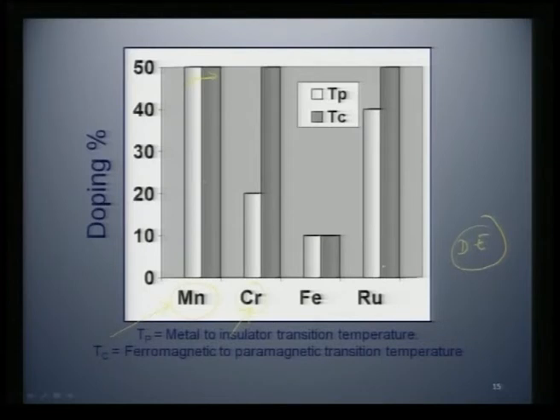Another interesting substitution comes from ruthenium. If you substitute ruthenium, the metal insulator transition is taken up to 40%, and you also see a strong ferromagnetism up to 50% of ruthenium. Therefore, something very interesting happens in the case of ruthenium substitution, but by and large, when you try to disturb the Zener pair, then the metal insulator transition is decoupled from the ferromagnetic to paramagnetic transition, that is TC.